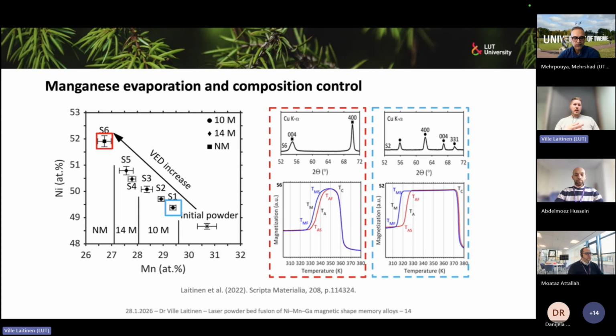For example, in one of my studies we have this initial powder amount, and then this S1 sample, which is 10M martensite, the preferred martensite variant if you want a functional nickel-manganese-gallium actuator. And then we have this S6, which is a non-modulated martensite. In an undoped nickel-manganese-gallium alloy with non-modulated martensite, the twinning stress is way too high. You won't be able to actuate it magnetically. So it is a passive material, but we can still use it as magnetic shielding, for example, in a real actuator.